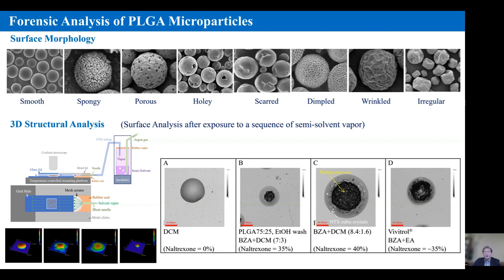So by studying the exact composition and the appearance, the surface morphology, we can guess what kind of processing was used. Also, again with the support of the FDA, we studied how to go a little bit deeper than the surface. There we analyzed the inside of the microparticle by using the so-called semi-solvent vapor method. We can selectively remove the surface PLGA and then see inside the core. This is one example, I think Vivitrol. If you remove the surface PLGA layer, you can see that naltrexone crystals accumulate in the center. That's why after the initial burst release, there's a lag time of several days, and probably this is one of the reasons. This is Vivitrol. This is another formulation we made in the lab.